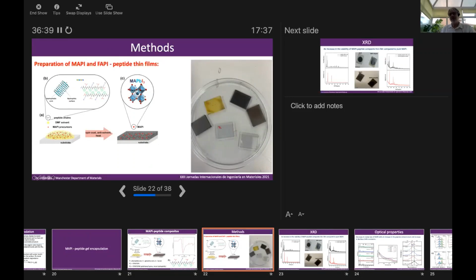We don't know whether this is just due to steric effects, due to the larger formamidinium ion, or due to the electrostatic effect, the additional charge in the formamidinium ion interacting with the amine side chains in the peptide. Either way, we saw that this was not going to work, so we've given up on the formamidinium for the time being, and we're concentrating on the methylammonium lead iodide. So we were able to make these quite nice films.